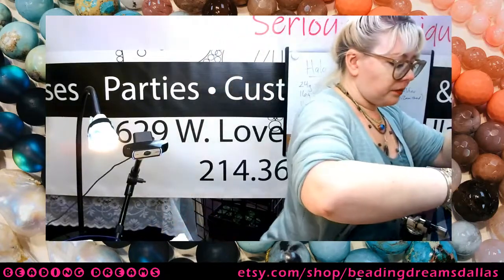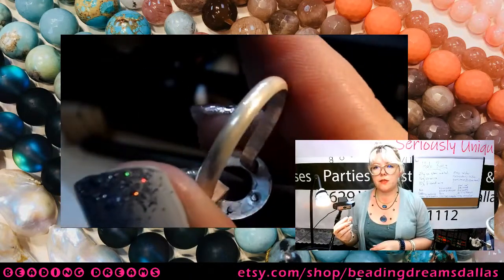So the piece stays in the pickle until it is clean, meaning basically all of the black crud is gone from it and it has acquired this surface finish, which is called pickle white. Okay, so basically that's a matte white surface finish that results from a layer of fine silver being deposited on your piece, because when you heat metal that is an alloy like sterling silver, the metal oxidizes, as sterling silver does. The part of the alloy that oxidizes is the base metal component. Okay, so it's the part that's not pure silver or pure gold.